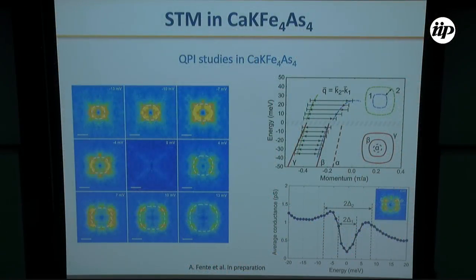In this graph, we have plotted the radial average conductance at the QPI vector as a function of energy, and we can reproduce the 2-gap structure that we have seen in the tunneling data, with exactly the same values. You may note that the signal doesn't go to 0 at the Fermi level, and I will discuss in a moment why.